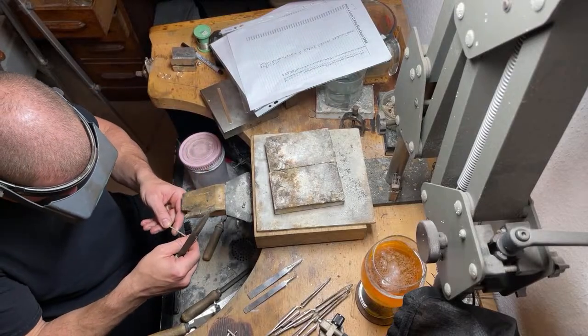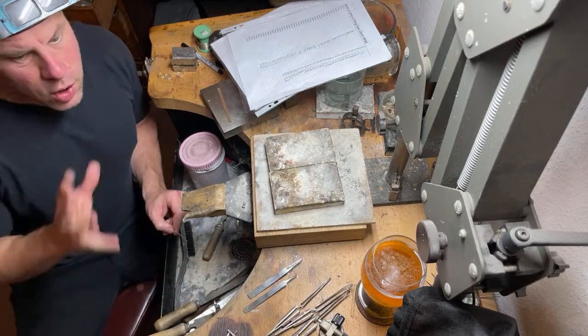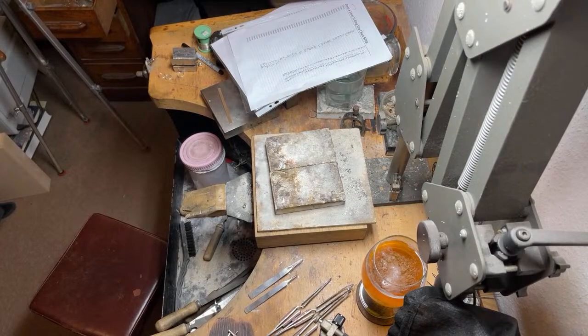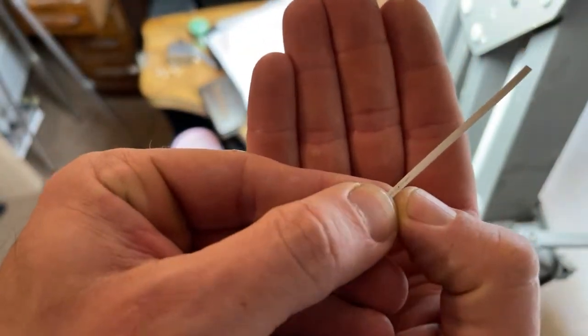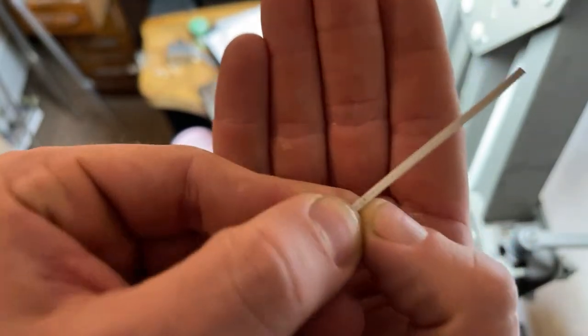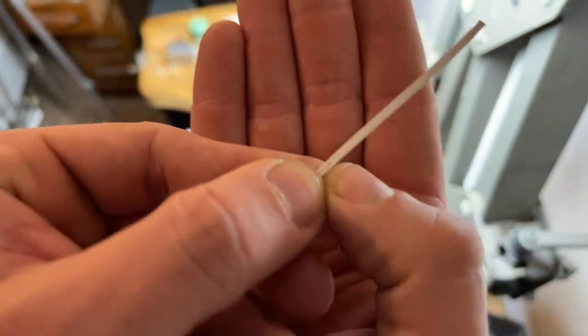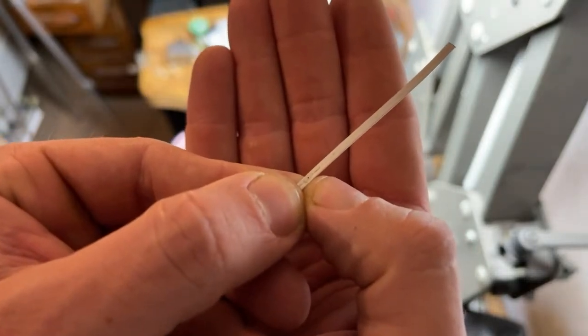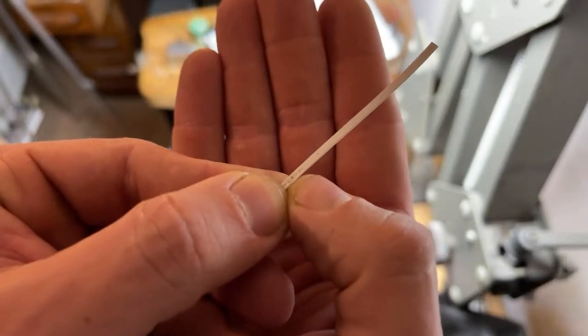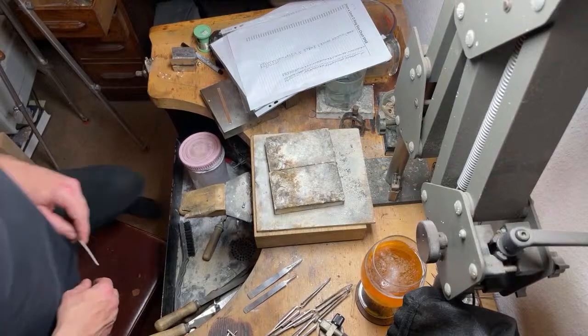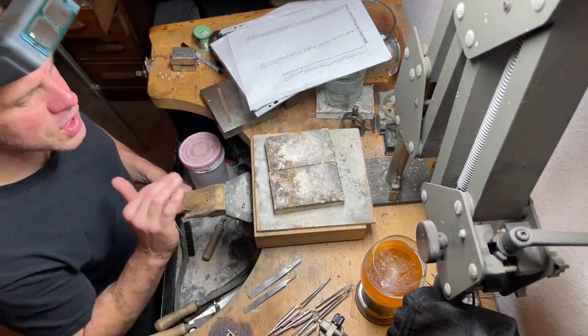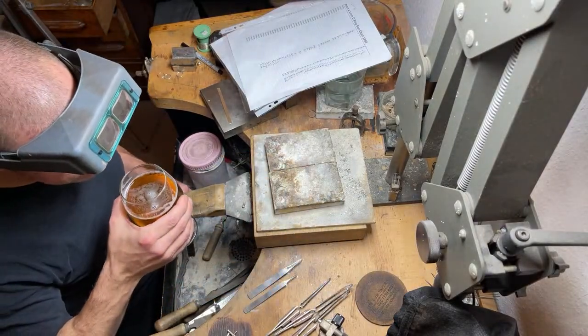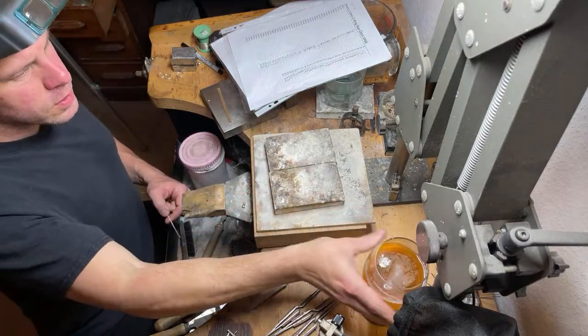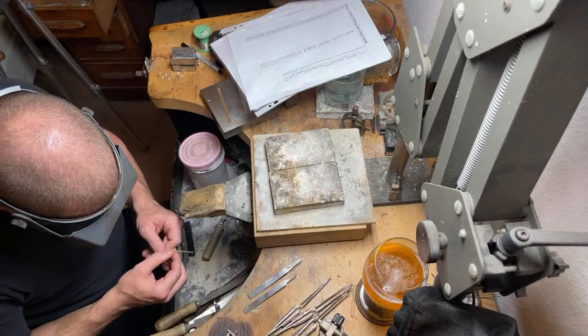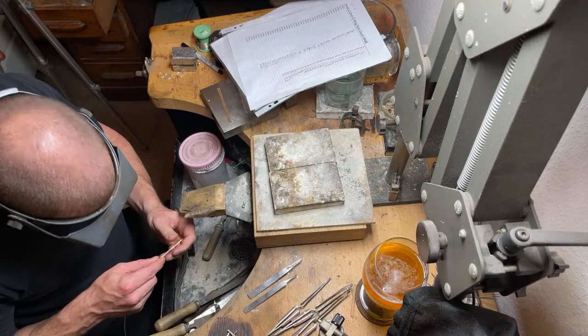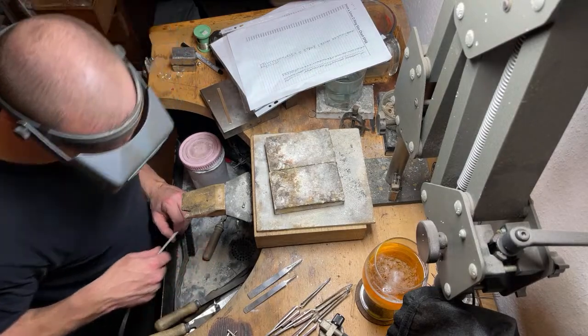And also what happens, I'll give you a little close-up of the porosity. It tarnishes, so it's not just porosity, it's porosity with black tarnish. Can you see it there where my thumbs are? See, it's not just porosity, I think that is basically subsurface. Water gets in if you quench it too quickly in water, and then eventually it comes to the surface. You're squeezing, probably it actually bubbles up. You end up with almost like little blisters because it's probably very close to the surface. First of all, it blisters, and then when it reaches the surface, you're rolling it out and it becomes wet. It's a really odd situation. 44 mil.